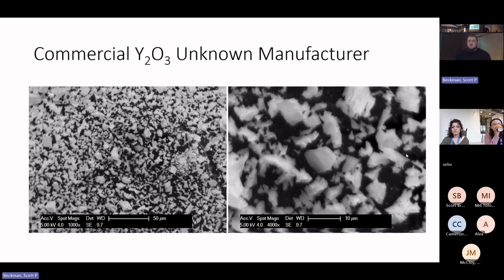What's your pellet diameter? So the pellet diameters that we did were 1 inch diameter, and they varied in thickness depending on what green body density we could get and how much sintering went on and how effective our densification processes were. So we also looked at our powders under SEM imaging.